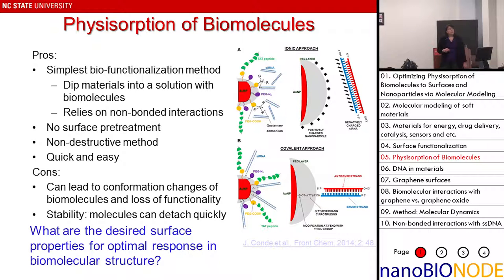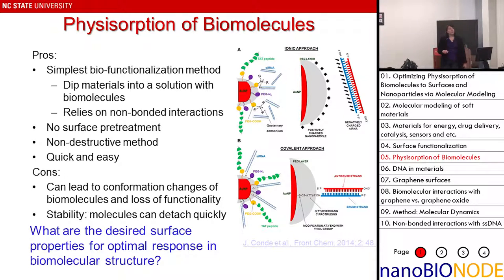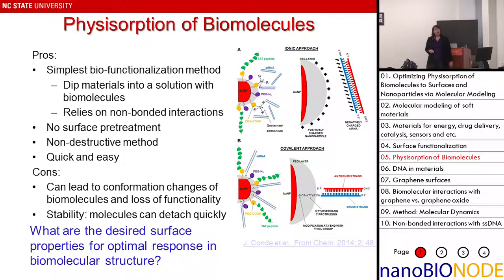With physisorption we have a lot of advantages. It's very easy — no surface pretreatment required. All you have to do is dip material into solution that contains biomolecules. It's not destructive and it's very cheap. However, the biggest issues associated with physisorption are that we don't necessarily know how the molecule is going to respond to a specific surface property. It may lead to conformational changes of biomolecules, which is detrimental to performance, and also stability — these interactions can cause molecules to detach quickly.